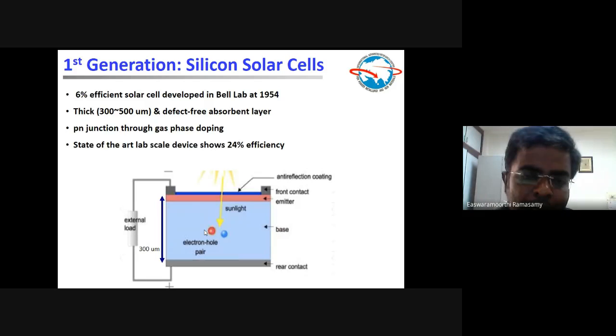Instead of bringing two different materials together to form a junction, in the silicon solar cell we simply take a P-type silicon and dope the top region with an N-type material, in this case phosphorus. So you create an N-type silicon layer, and the PN junction is formed. So take a wafer, expose it to phosphorus gas, create the N-type doping, and you form a PN junction.